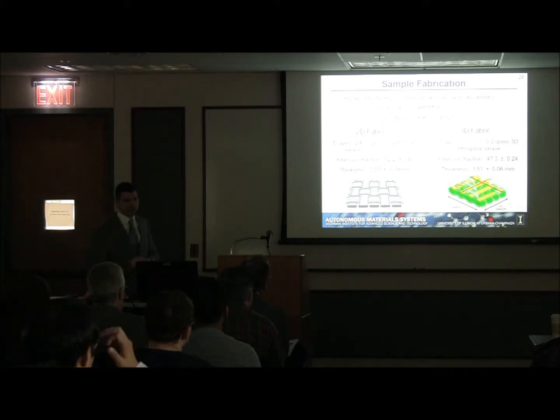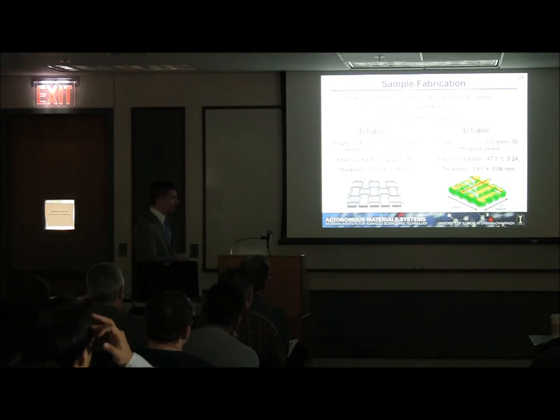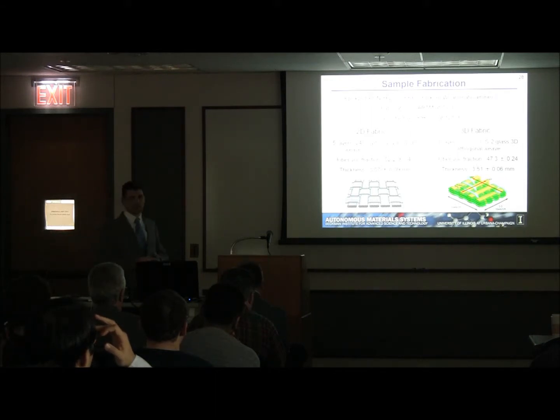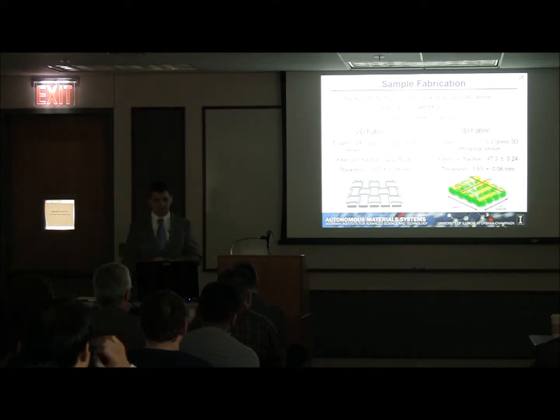Again, it's an S2 glass and it's woven orthogonally, like you see in this picture here. And so it's important for us to match the materials, so the fiber type and the epoxy type, as well as the areal densities of the fabrics, to minimize the differences in the architecture as much as possible. These yielded fiber volume fractions of about 47% and thicknesses of about 3.5 millimeters.